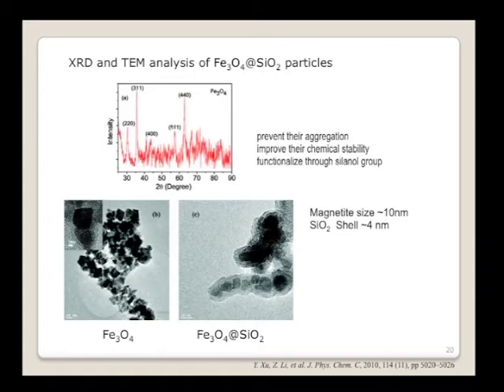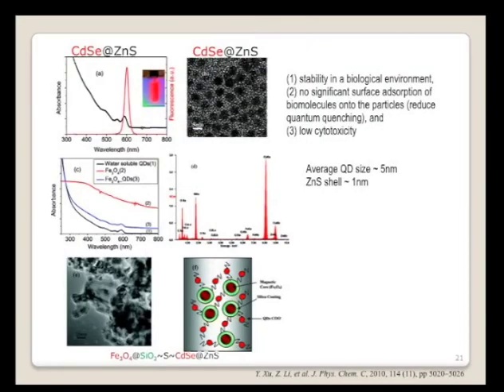This is a TEM image of the magnetite nanoparticles. You can see the size is around 10 nanometers. This is the composite, actually iron oxide coated with silicon oxide. This shell you can see is around 4 nanometers. Okay, we made one part. This is a magnetic particle.